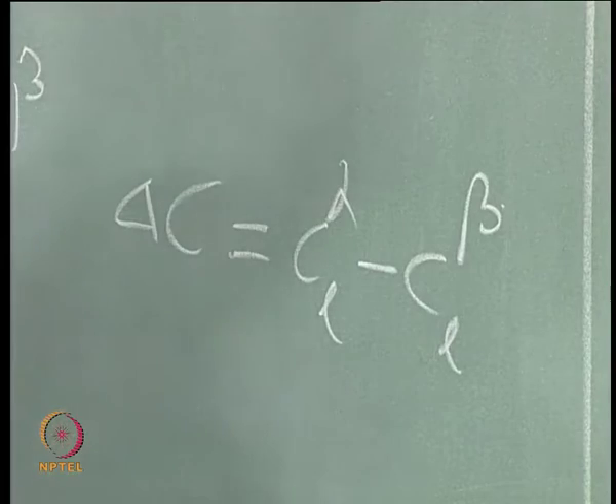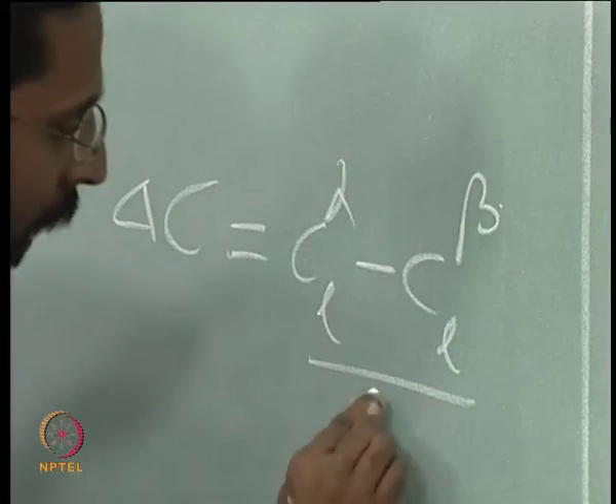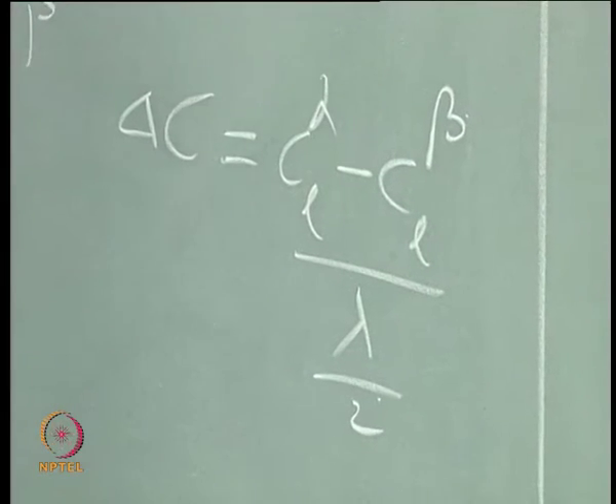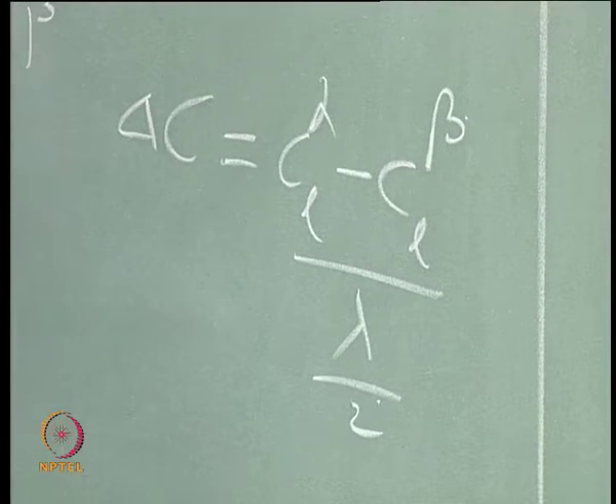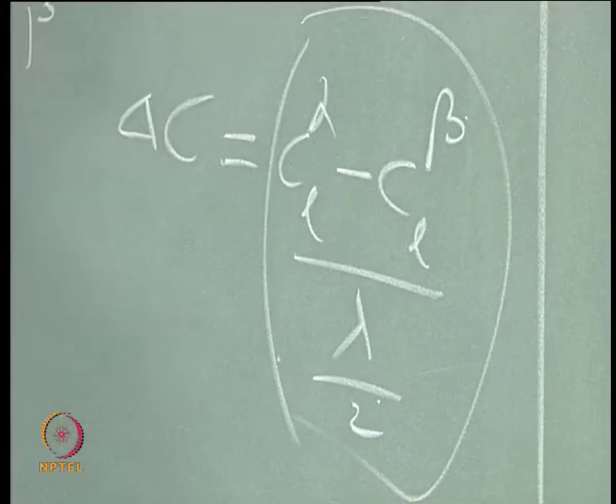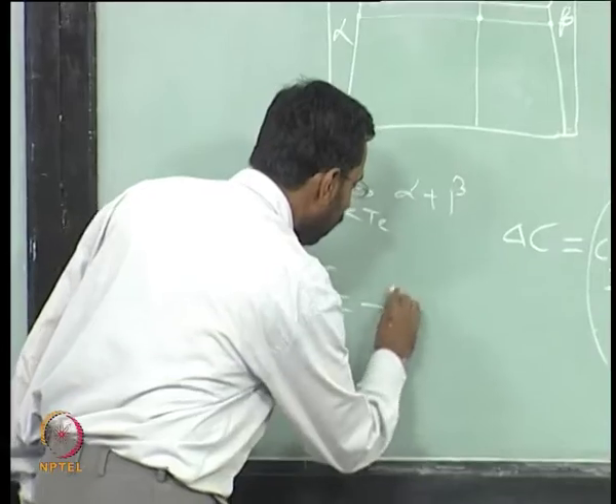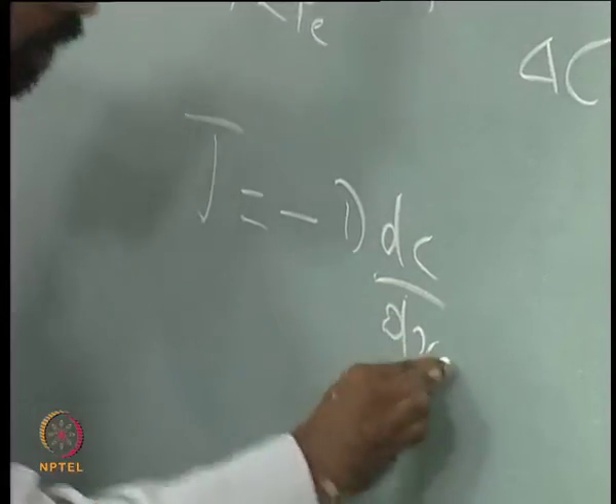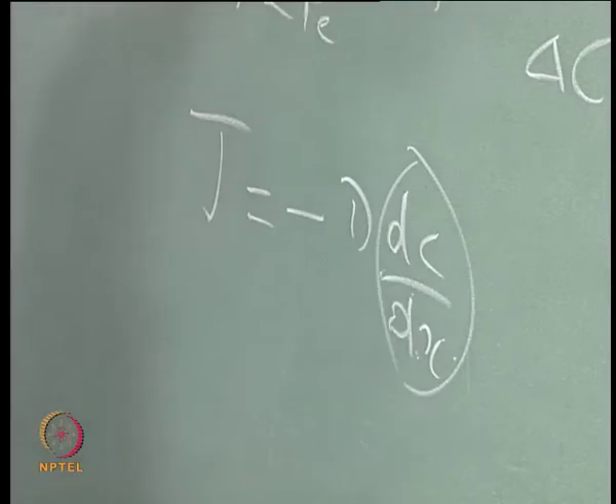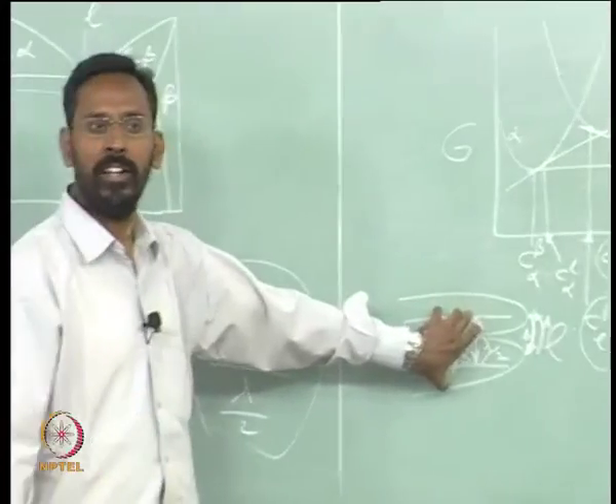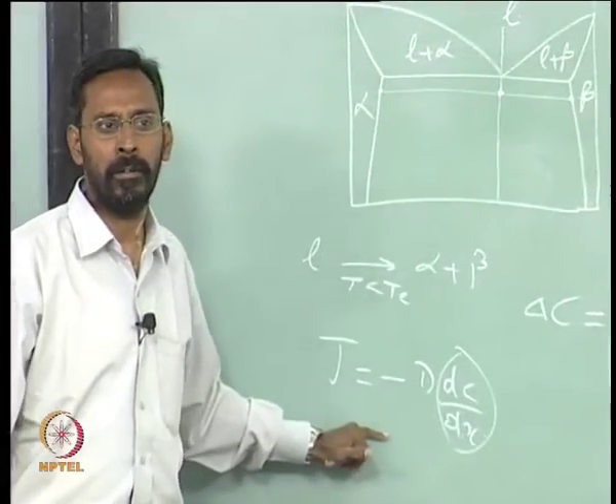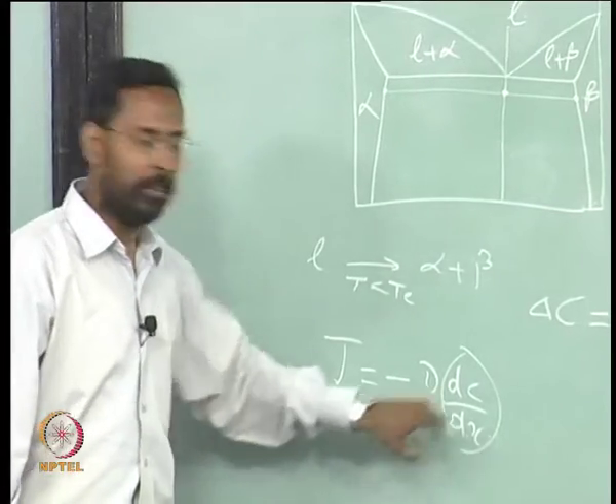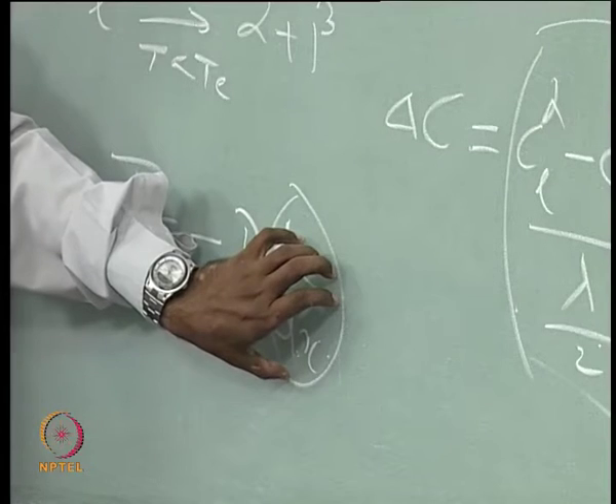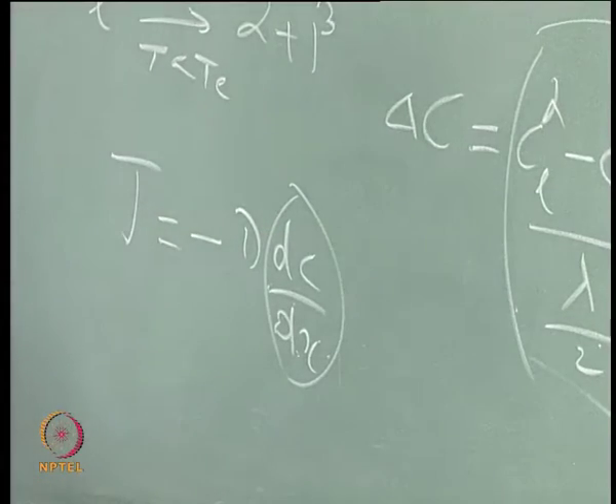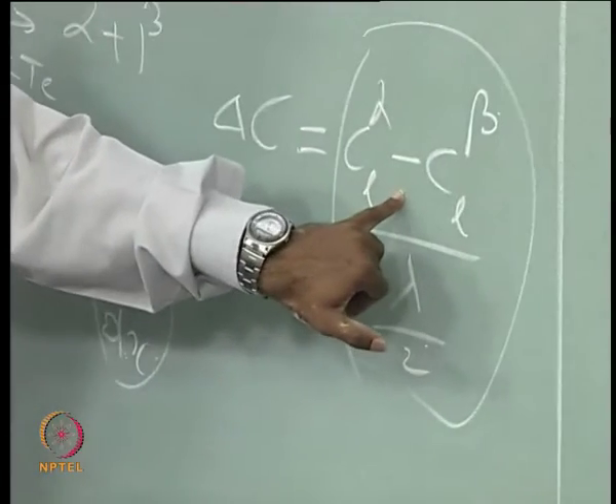This and the gradient, concentration gradient, can be written as this by lambda by 2. This is the actual concentration gradient, and if you say diffusion J equals minus D dC by dx, the dC by dx for the flow of atoms comes from here. Once the nucleation has taken place, the growth is decided only by diffusion, isn't it? And diffusion needs a gradient. If there is no gradient, if the gradient is zero, there is no diffusion. So this gradient is provided by this.